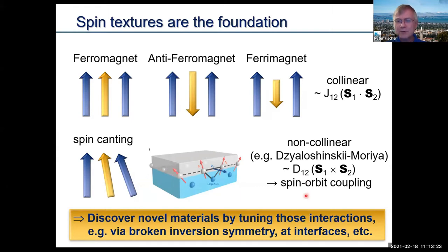And of course, this has to do with spin-orbit coupling, and it has also some constant that goes with this, that scales the strength of this. Now, the thing is, you can play with those two. Basically, by bringing the symmetric and the antisymmetric exchange interactions into the game and tuning those interactions, you can really discover new materials where the spin texture will not look anymore either parallel, antiparallel, or canted, but it could be anything in between. And this is a path for discovering novel materials by just tuning those interactions. And it has to do with broken inversion symmetry that happens, for instance, at interfaces.